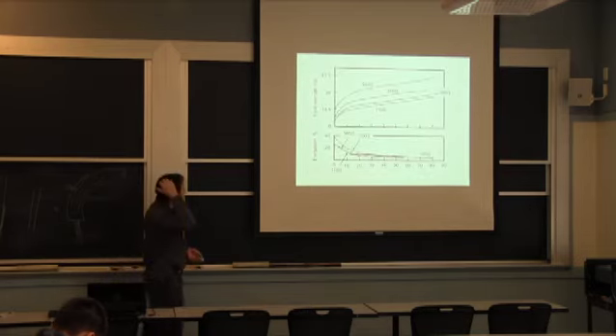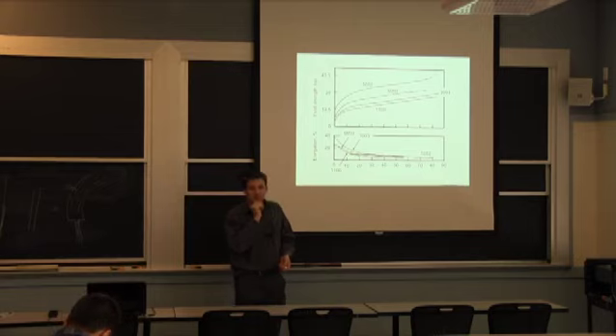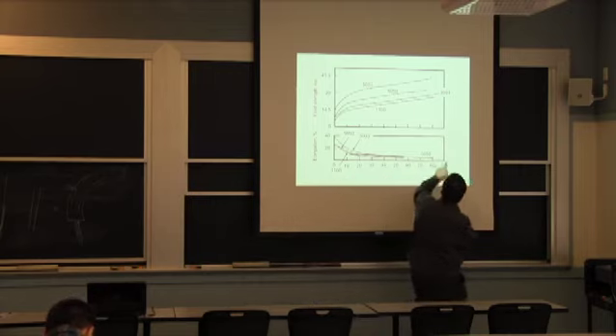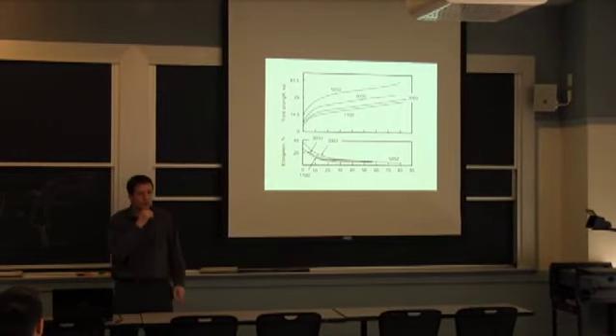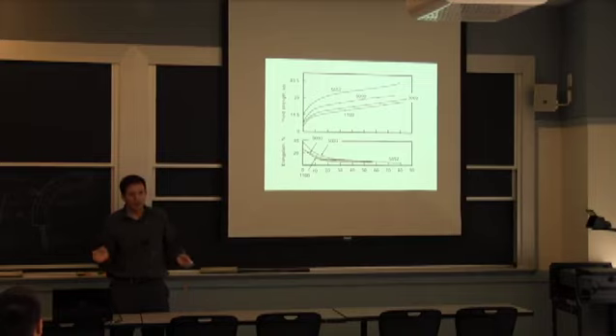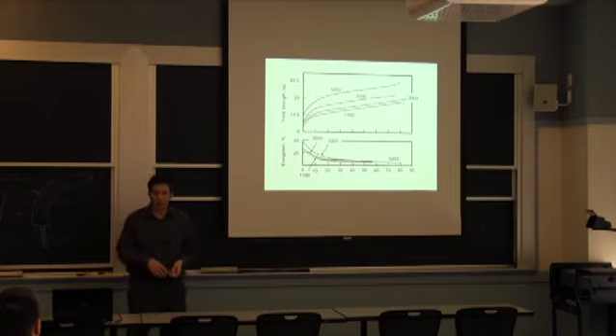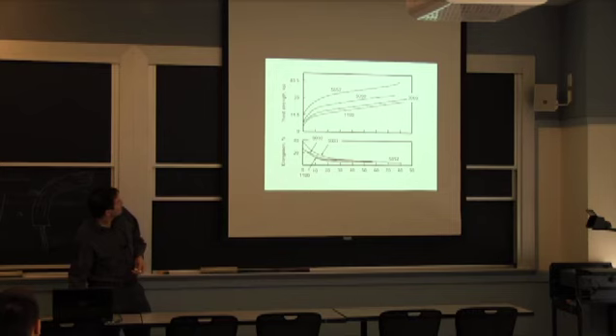This is just really to give you an idea for the alloys that are deformable, how much strain you can actually put in them and still increase the yield strength. Any of them, we're up here at 100%, and it's still going up. So it takes of the order of 200% before you actually reach a fully hard condition of these alloys. So when we're looking at a stress strain curve, that's an exemplification. If I report 30% elongation at break, it's from tension. If I have a rolling application, I can deform that aluminum to a much greater extent. So it's just to give you an idea.